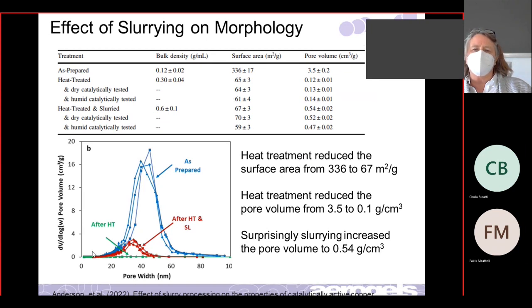We just published this and the reviewers were like, why? And we're like, we don't know. It's odd. We repeated this several times, so it wasn't a fluke. For some reason, after it's been in the water and it dries out again, you get some of the pore volume. So first thing is it survived the slurrying. No worse off. In terms of surface area, similar to just heat treated and better in terms of pore volume. So that was the first step.